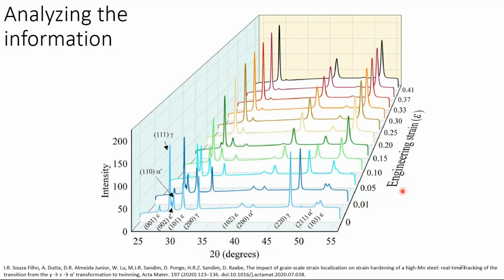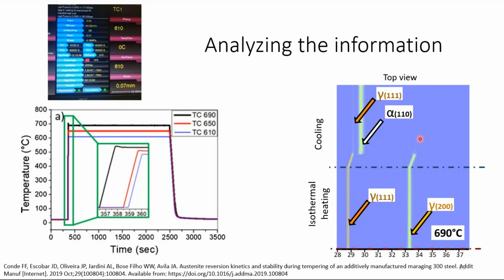You can say here that you're applying engineering strain, or you can apply heat, or both at the same time. And then you need to analyze that information and make some quantification. This is another example. We apply isothermal heat treatments for 30 minutes. There are here 3 temperatures: 610, 650, 690. Okay, I'm only going to show you the last case, starting from the isothermal heating, from the high point when you reach the temperature, and then you are going to transform a complete martensite structure to austenite. So in that step, starting from here, you are going to have only austenite,